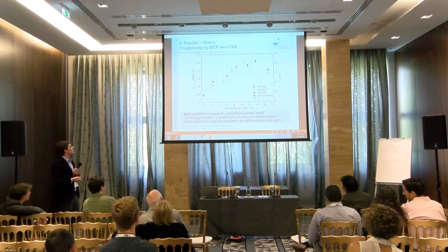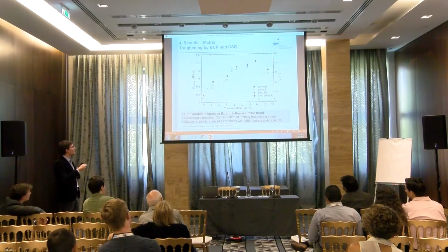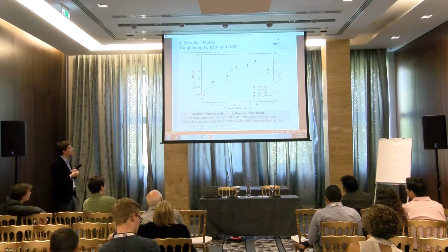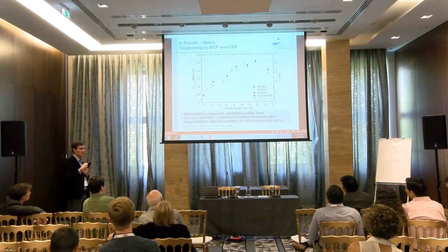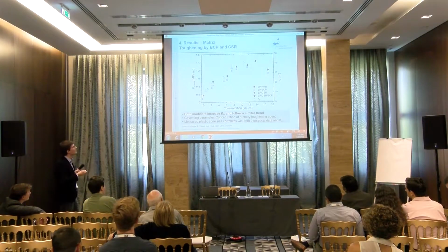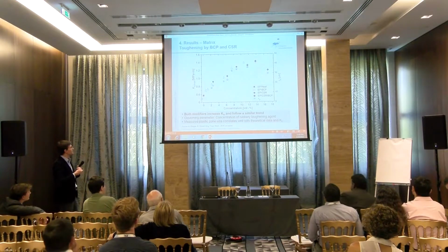The same works with the fracture toughness. This is all from the matrix, to point out. It doesn't matter what kind of modification you use. Is it block copolymer, is it a core-shell rubber, or a hybrid in the end? You get a certain increase in fracture toughness, and then it bottoms out.